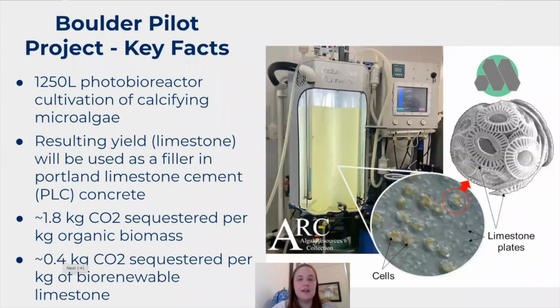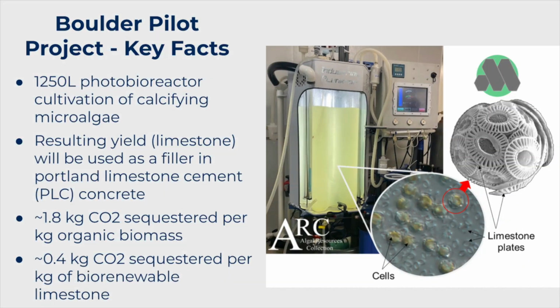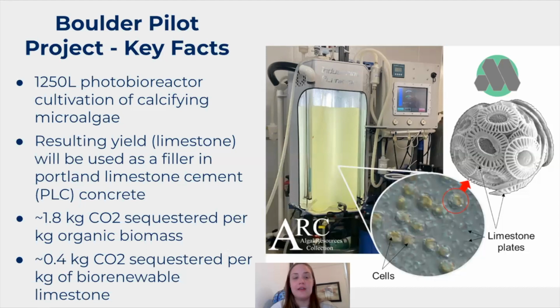Portland limestone cement is super popular nowadays, where you can replace about 15% of clinker content with limestone, which gives you some pretty significant CO2 reductions. And in the case that our limestone is added as the limestone component, there are further CO2 reductions since we're starting with a carbon negative filler material. As the cells are growing through photosynthesis, they sequester about 1.8 kilograms of CO2 per kilogram of organic biomass. And then in terms of the mineralization reaction, where they make limestone, they sequester about 0.4 kilograms of CO2 per kilogram of mineral limestone produced.